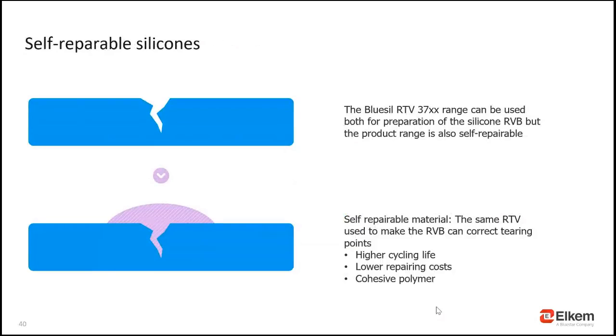To increase cycling life, Elkem Silicones for infusion molding were developed to support our customers to have a more and more economic process. One of the main causes of silicone mold failures is that the contact surface is impregnated by resin and develops a brittle aspect, tearing at the molding. To avoid such defect, Elkem RTV silicones have a high chemical resistance and self-repairing performance.